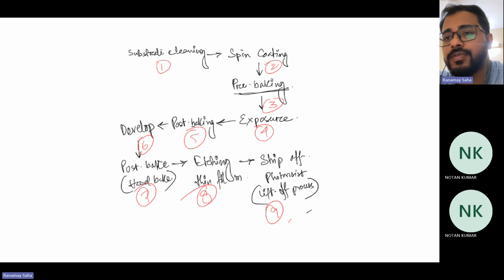Suppose you are doing positive photolithography and then you have done the developing process where the material has been washed out of the undesired region. Now, in those regions, the substrate is exposed, right? And in the masked region, the substrate is unexposed because the photoresist coating has stayed back. Now, if you want to transfer those patterns into the substrate surface, the uncoated or exposed substrate surface, you do the etching process. Okay? So what happens? You will just have the circuitry, maybe for example, inscribed into the silicon surface.